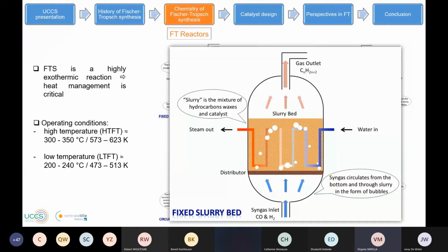So we have the slurry bed reactor. In this reactor, the syngas comes from the bottom of the reactor and circulates through a mixture of hydrocarbon and the catalyst, and then it reacts to form normally long chain hydrocarbons. And through this mixture of hydrocarbon and wax, we have circulation of water for cooling, to avoid the exothermicity of this reaction. And all the light products go through the top of the reactor.